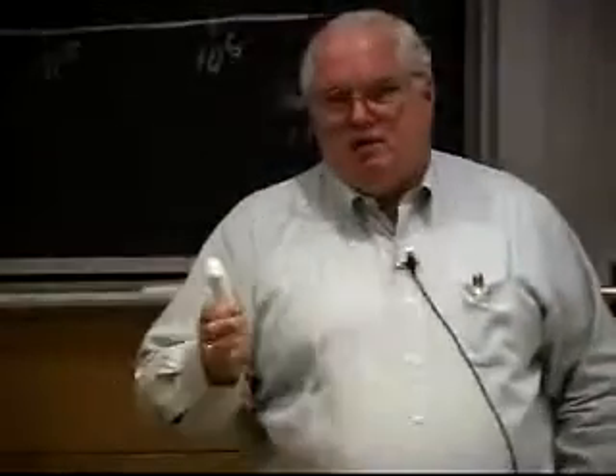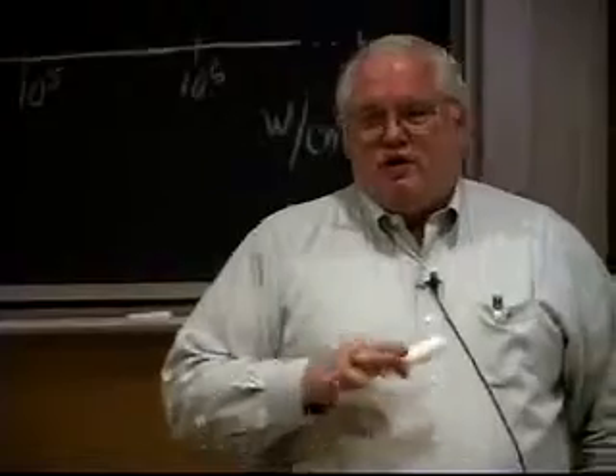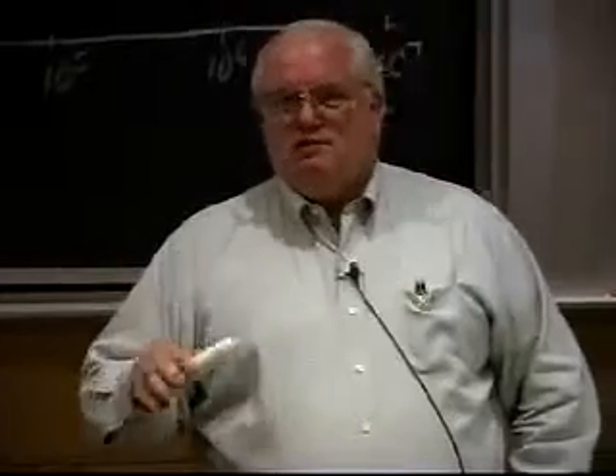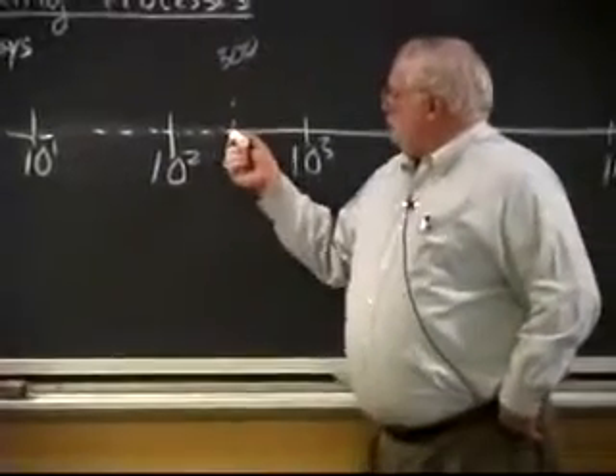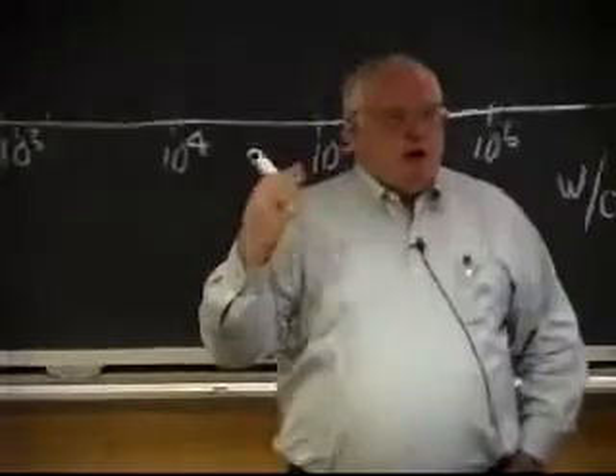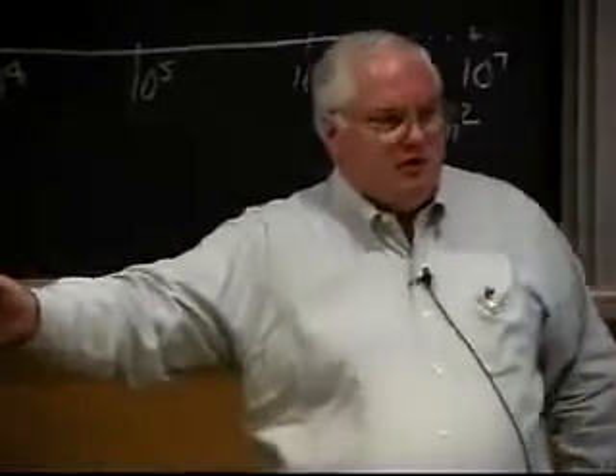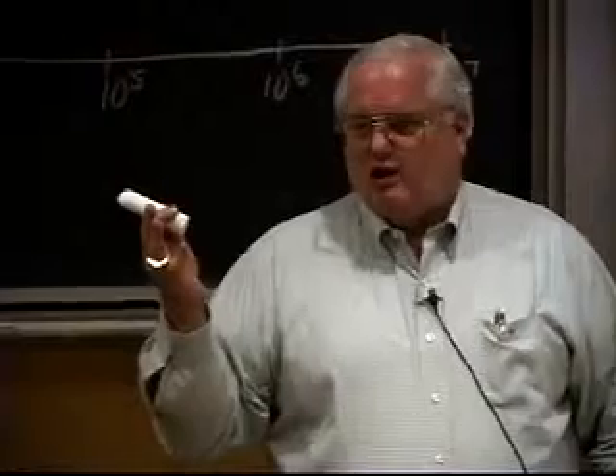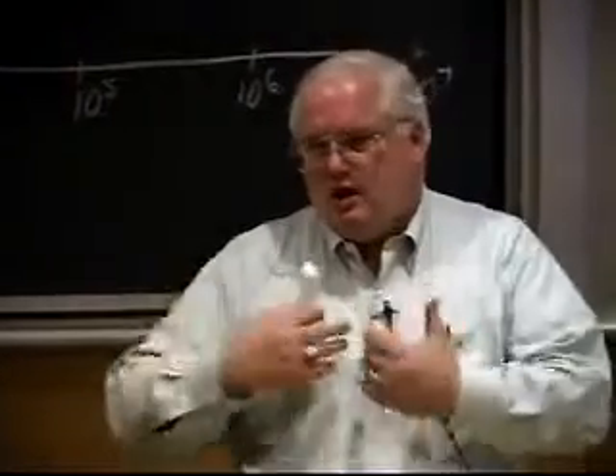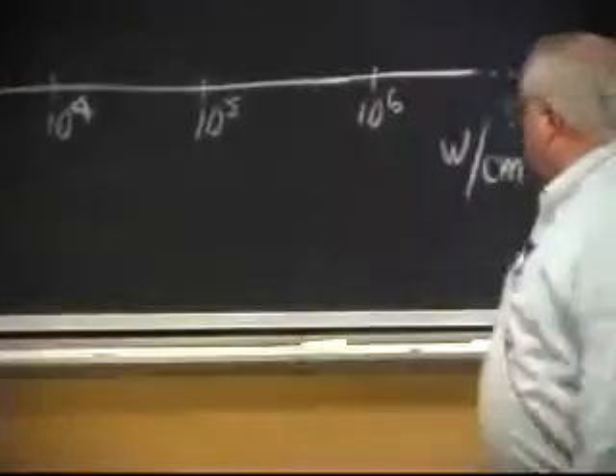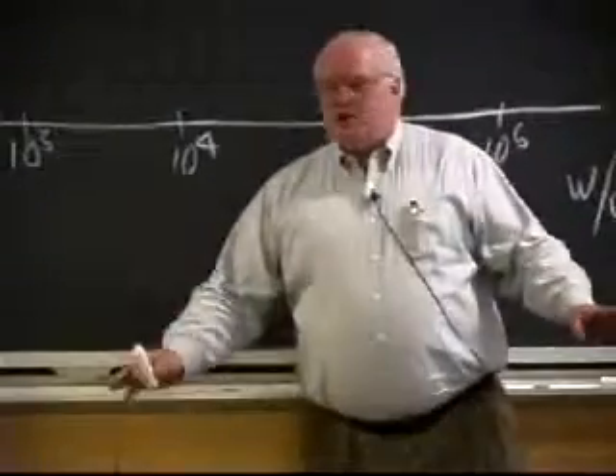Now, if I was talking tin or something like that, a very low melting metal, or a very low thermal diffusivity material like plutonium, you could. But most common metals, copper, aluminum, iron, titanium, nickel, if I have a surface heat flux of 300 watts per square centimeter or less, I cannot bring the metal up to its melting temperature because it conducts the heat away. The thermal conductivity of the metal is such that it will conduct the heat away faster than I can store it on the surface. I'll prove that to you next week in my most dangerous demonstration yet.